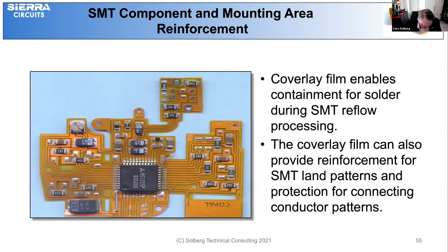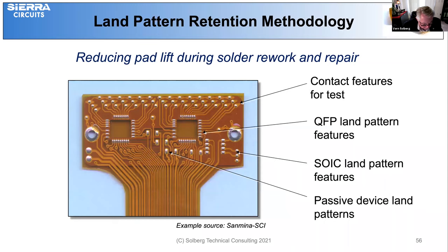Now getting into component placement on flex: land pattern features for surface mount devices are susceptible to peeling or lifting when excessive heat is applied during rework or repair activity. Heat applied during initial solder assembly may not be a concern, but heat applied to desolder and resolder components can weaken the copper adhesion at the base dielectric film, resulting in pad lift.